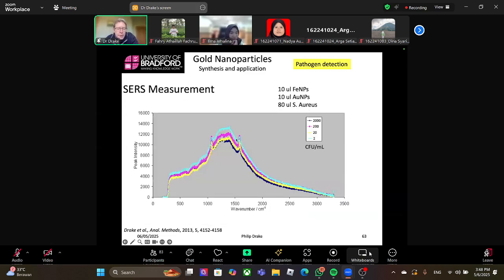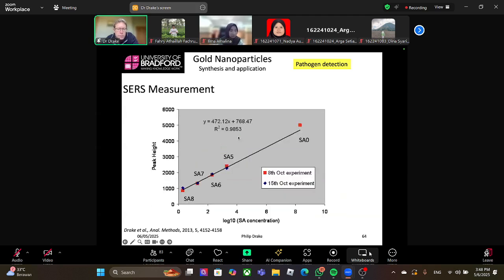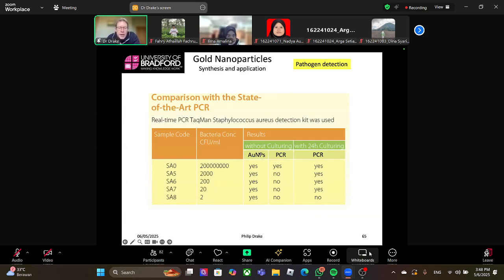The SERS measurement, those particles give us those two characteristic peaks, and we can link the peak height to the concentration. So what we get is a linear dependence between SERS peak height and the concentration of S. aureus, at different concentrations. With the gold particles, we can detect 2 CFU per mL of S. aureus. Standard PCR can detect 200 million. If you culture the bacteria for 24 hours and run PCR, you can detect 20 CFU, but even then you can't detect 2. With the gold nanoparticles, you can detect all the way down to 2 CFU per mL.